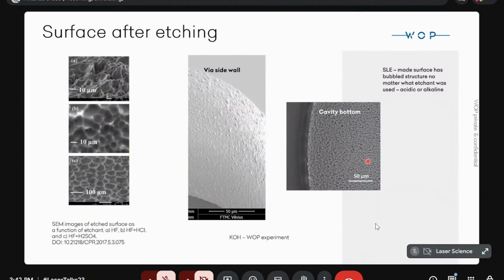What is important to say is that, as I mentioned, the people from semiconductors and especially from electronics ask for a very smooth surface. But selective laser etching cannot make the surface very, very smooth, meaning Ra 100 nanometers or something like that. You can see that, regardless of whether it is acid etched or alkali etched, the surface has a kind of bubble structure.